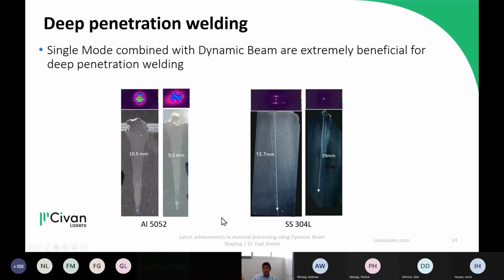Now we can also increase the power. This was done with our standard OPA6 with a maximum of 10 kilowatt, but we have today 28 kilowatt and 100 kilowatt lasers. And we anticipate that with the higher power, you can get really high speed, very high quality, deep penetration welding, both in aluminum and steel.